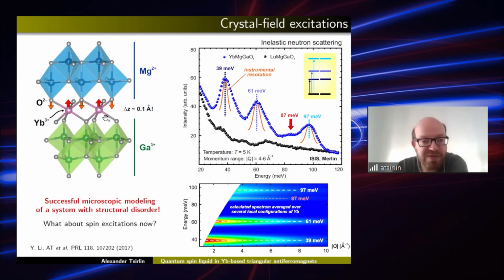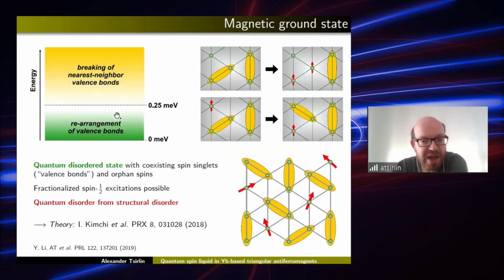So we do have a lot of structural randomness in the system, and that has its implications for the magnetic excitations. Because when we looked at these low energy excitations in more detail, we actually were able to describe them with 2 different terms. One of them are these generic excitations of the quantum spin liquid, so the breaking of the singlet into 2 spinons. But on top of that, it turns out that there are some unpaired spins present down to lowest temperatures, and they can change places with the singlets, and this is what dominates the low energy part of the spectrum.